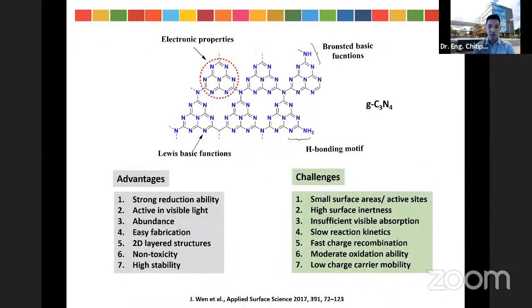So let me introduce you to the graphite carbon nitride materials. The graphite carbon nitride material, or g-C3N4, has a layer structure similar to graphite and presents interesting and unique physical chemical properties due to its structure having the s-triazine link. However, the electronic and chemical properties of this material are not so good due to its very poor conductivity. So recently, the photocatalytic activity of the g-C3N4 has been tested for various photocatalytic applications, for example, hydrogen generation by water splitting or degradation of organic pollutants in wastewater.